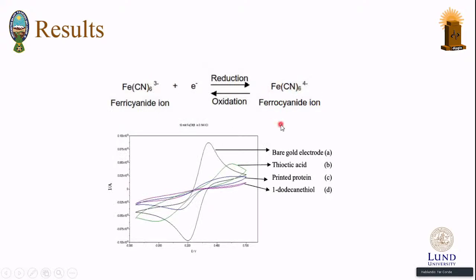As I said before, we are using a reversible redox couple, which is ferrocyanide and ferricyanide. The oxidation occurs in this part, where we have a positive current, and the reduction occurs in the lower part. The electrode in this part shows a clean electrode, so we don't have anything over the electrode. When we perform the insulation, we use thioctic acid, thiourea, or even electropolymerization of tyramine. We can see that it is reducing the response of the reversible redox couple here. And then every time that we add different components on the layer, such as the imprinted protein or antibody, and finally 1-dodecanethiol in order to fill the pinholes, we get a flatter figure.